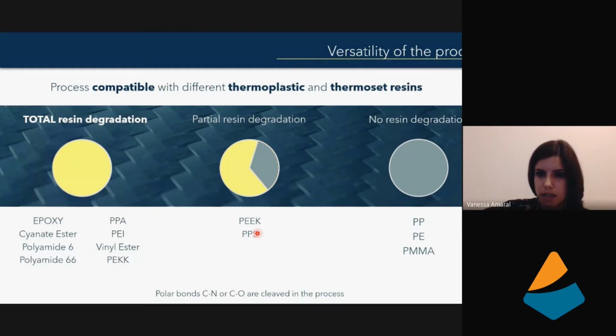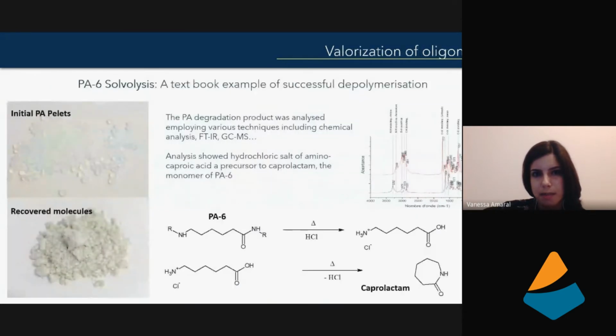good resin degradation. However, because of how the process cleaves the bonds, it's not compatible at all with PP, PE, and PMMA. However, we do have a large part of the market, especially regarding the epoxy resins, that can be well degraded in our process.